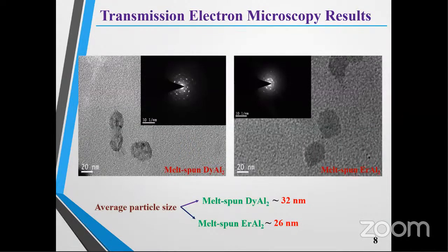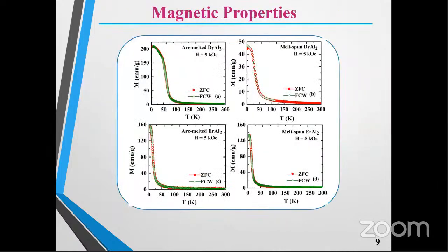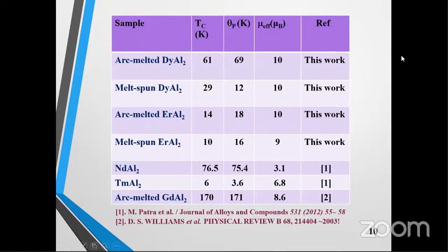Then from the transmission electron microscopy results, I have calculated the average particle size, which is about 32 nanometer for the melt-spun DyAl2 sample, and about 26 nanometer for the melt-spun ErAl2 sample. And talking about magnetic properties, here is the transition. We can see the transition temperature of all four samples. The zero field cooling and field cool warming plots merge with each other for 5 kilo-oersted field for all of the samples. And from here, we can see the transition from paramagnetic state to ferromagnetic state. I have listed the Curie temperature, paramagnetic Curie temperature, and effective magnetic moment of some of my samples and a few other samples. Here we can see the Curie temperature has been reduced for melt-spun samples.